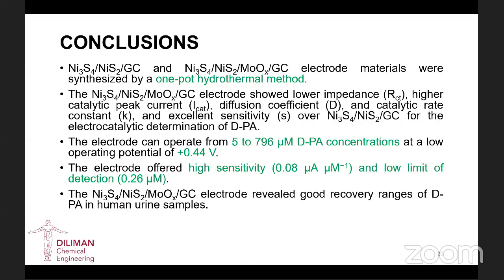Okay, so in conclusion, these two materials were synthesized using a one-pot hydrothermal method, and the impedance, catalytic peak current, and other parameters were calculated and compared to results in the literature, and they were considered better in terms of the parameters listed here. And yeah, so that's all. And the thing is, we were able to use this on testing human urine samples. So I think that's all.